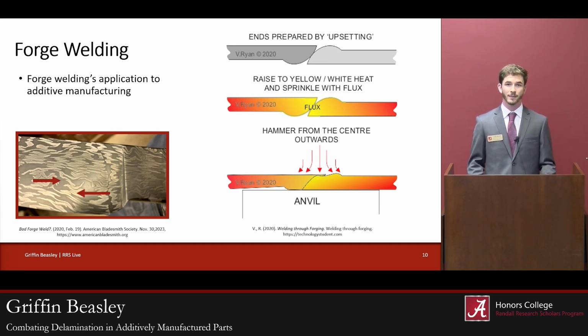Now, for additive manufacturing, we intend to view the layers in our part created from SLM very similarly to the layers used in a Damascus billet. And we believe that if we put this additively manufactured part through the same kind of forge welding process that Damascus is put through, we will see an improvement in the mechanical properties that the part possesses.